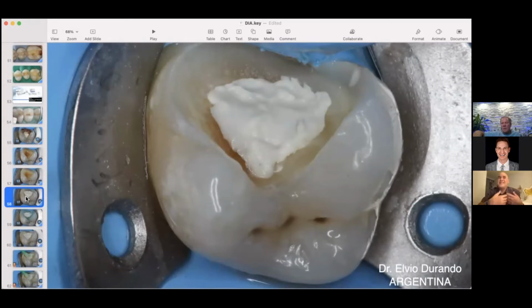And if it doesn't cure, the way Theracal stays in place, I don't want to say bonding, is because you need to leave the dentin moist. And this is very product specific, okay? This is specific to Theracal. You need to leave the dentin moist. When you apply it with your syringe and you have that moisture on the dentin, Theracal is going to be able to flow and have intimate contact. Like if you take two glass slides and you add a drop of water and you put them together, it's very difficult to split them apart because of that connection, that intimate contact. That's basically what we're trying to achieve here.